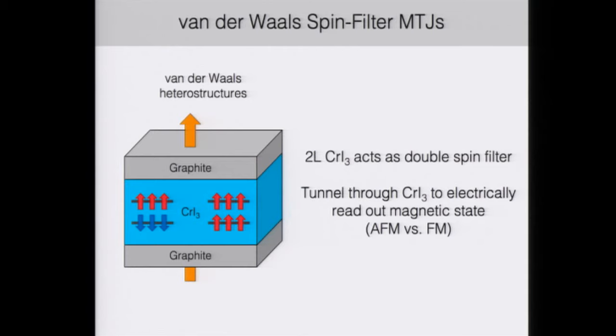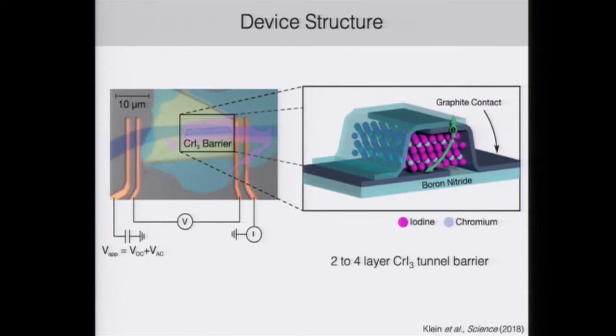So we fabricated these van der Waals heterostructures inside our glove box, where we use top and bottom boron nitride to encapsulate our device, and two graphite contacts, which we aligned such that the only overlap area would be through the chromium iodide barrier, so that electrons have to tunnel vertically through a barrier that we fabricated to be 2 to 4 layers thick.